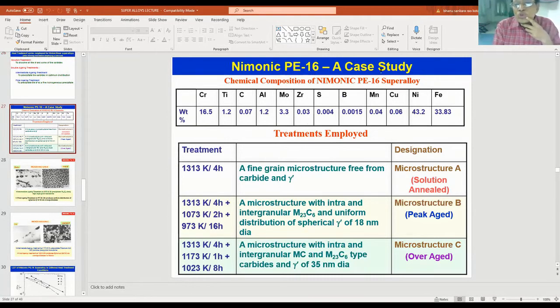In the case of the Nimonic PE-16 superalloy, which is a very simple superalloy, you see that this is a nickel-iron based superalloy. Earlier I was telling that the base is, in nickel and iron, each case less than 50%, but combined they exceed 50%. So we call it a nickel-iron based superalloy. To that, chromium of 16.5 is added for oxidation resistance, and titanium and aluminum, 1.2% each, are added to form your gamma prime.